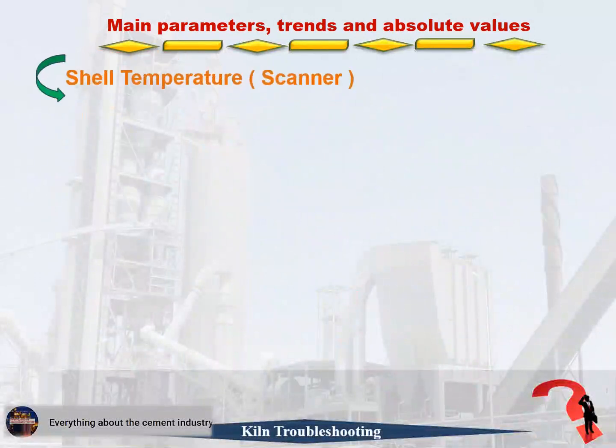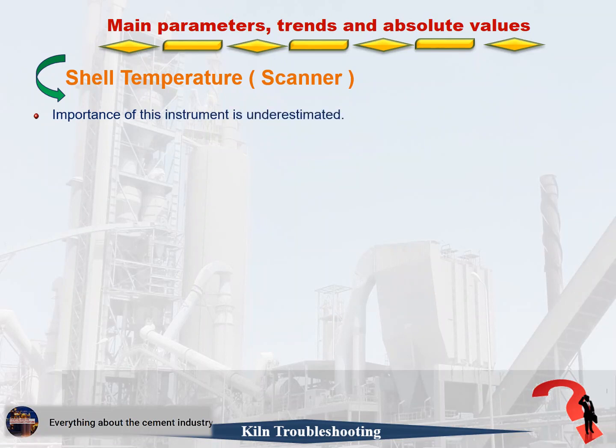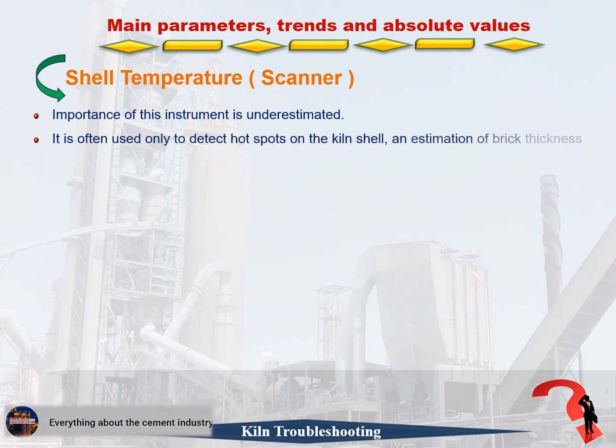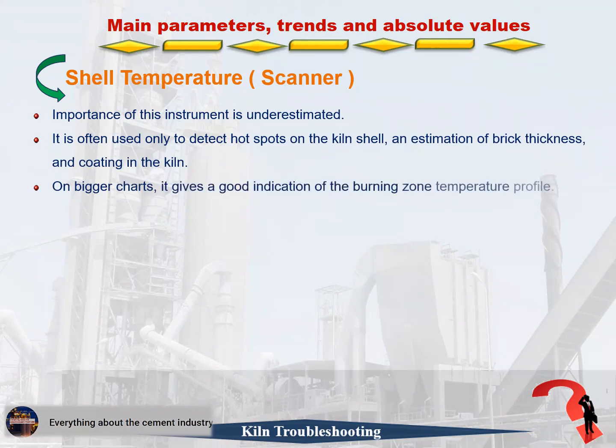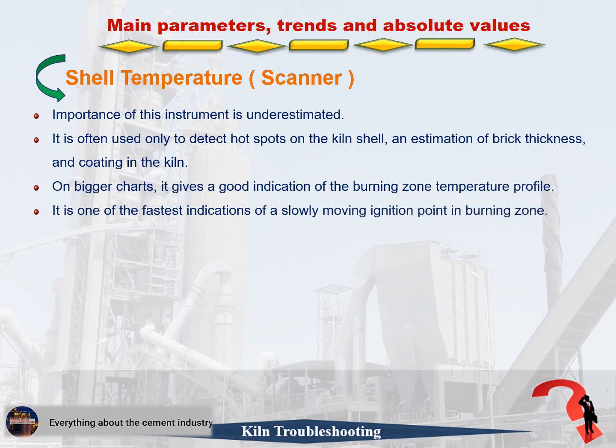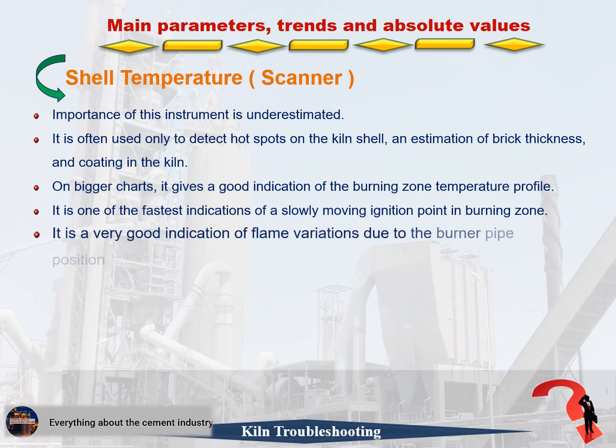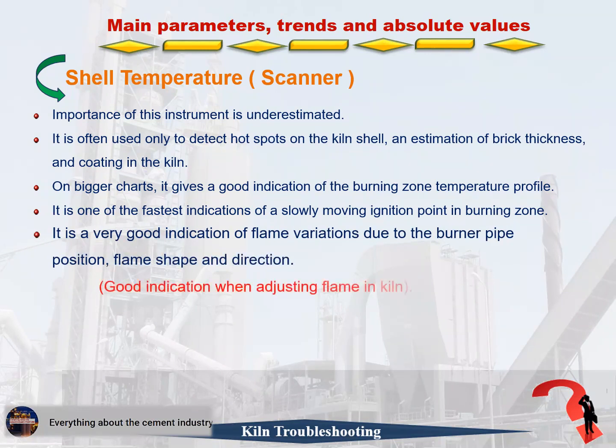Shell temperature scanner. 1. Importance of this instrument is underestimated. 2. It is often used only to detect hot spots on the kiln shell, an estimation of brick thickness, and coating in the kiln. 3. On bigger charts, it gives a good indication of the burning zone temperature profile. 4. It is one of the fastest indications of a slowly moving ignition point in burning zone. 5. It is a very good indication of flame variations due to the burner pipe position, flame shape, and direction. Good indication when adjusting flame in kiln.